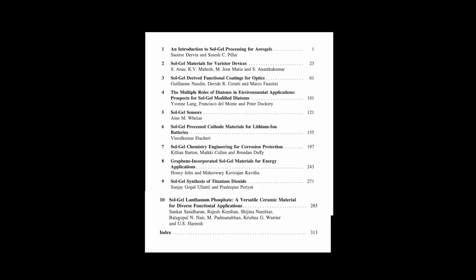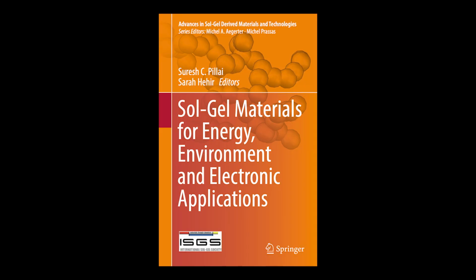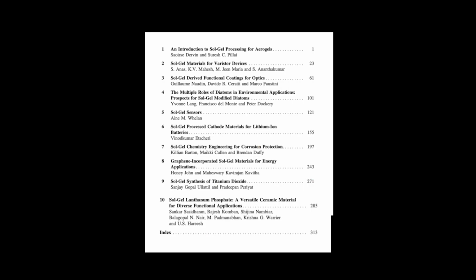Right. Let's focus on how these modified diatoms are being used specifically to help clean up the environment. What are the key applications there? The primary environmental uses discussed are photocatalysis and adsorption. For photocatalysis, diatoms act as incredible, naturally high surface area supports. Researchers coat the frustules with sol-gel-derived TiO2 nanoparticles using precursors like titanium isopropoxide. The unique architecture of the diatom doesn't just offer a massive surface area for the TiO2 to sit on, it can also help scatter and trap incoming light, enhancing the photocatalytic efficiency for degrading organic pollutants in water.